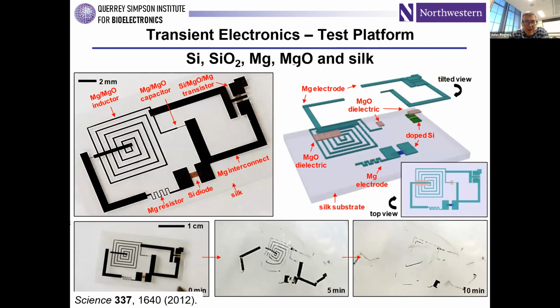And here's an example of that. We've taken silicon as a semiconductor, combined it with silicon dioxide as a gate insulator, magnesium as a conductor, magnesium oxide as an interlayer dielectric, and then we're using purified silk fiber cast into thin film form as a substrate and an encapsulation layer. Put it all together in patterned form, and we can create RF oscillators, in this case a Colpitts oscillator that combines a lot of the building blocks that you might think about for more sophisticated integrated circuits: an RF diode, silicon MOSFET, resistor, inductor, capacitor, and interconnects, and so on. The key defining feature here is that all of the constituent materials dissolve completely in an aqueous environment.